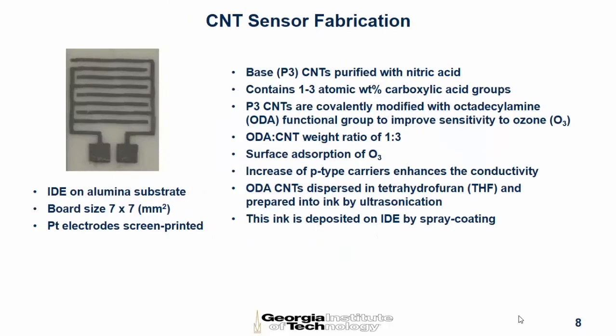So now it comes to our sensor. What we have is a pair of interdigitated electrodes on an alumina substrate. The whole size of the substrate is about 7 millimeters squared. And we have platinum electrodes screen printed on this.